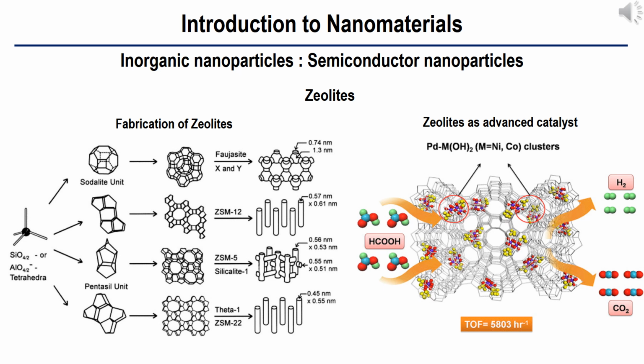Due to high surface-to-volume ratio, and size or shape selectivity of single molecule or molecular clusters, various zeolites can be used to control the chemical reaction. When incorporated with noble metals inside, zeolite is turned into advanced catalyst. For example, as shown in the right figure, palladium-nickel or palladium-cobalt clusters on the zeolite can turn the formic acid into hydrogen and carbon dioxide gases. This is promising in the production of hydrogen for fuel cells.